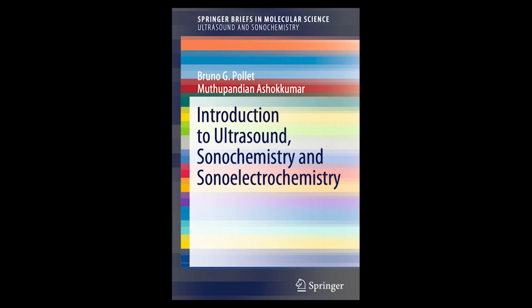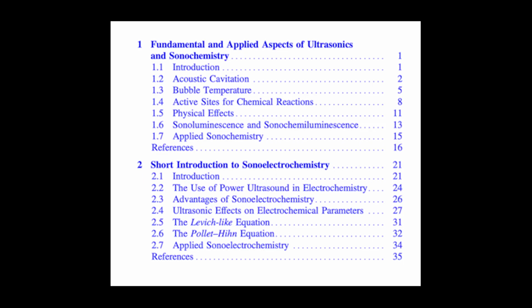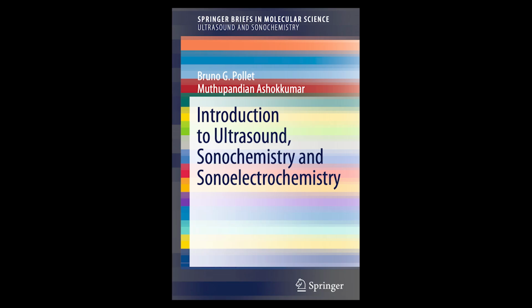For instance, some heat does conduct away into the liquid shell, even if it's fast. The gases inside the bubble also conduct heat. Makes sense, energy leaks out. Right, and maybe the most significant factor they often ignore, especially if there are other molecules inside the bubble, is the energy used up by endothermic chemical reactions. The chemistry itself uses some of the heat. Exactly — if molecules inside the bubble are breaking apart, pyrolysis, that process requires energy, it absorbs heat. So some of the compressional energy goes into breaking bonds, not just into raising the temperature.